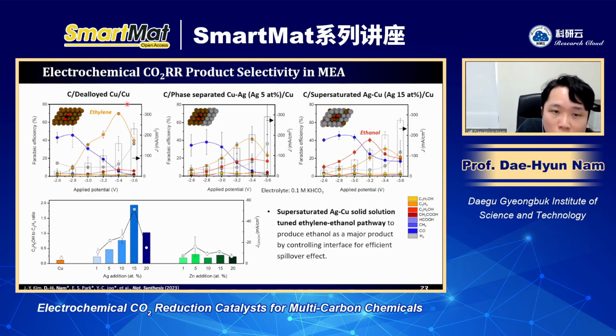And if we put the silver in it, and if we look at the 5% one, in the case of 5%, the low potential range is similar. The major product is CO. And although the silver 5% lowers the ethylene from 70 to 40% FE, there is no high FE for ethanol.